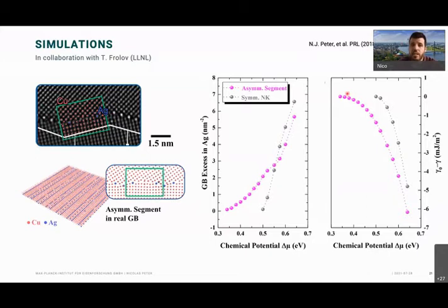This is also reflected in the grain boundary energy, because once the symmetric one takes up silver, the energy goes down very rapidly compared to the asymmetric one. So that was a nice observation, which kind of explained a little bit to us why we see certain features. So why is the silver mostly going to the symmetric portion of the boundary? It's just energetically much more favorable once they are there. So that means it's likely because we just initiate or form these because it's energetically much more favorable.